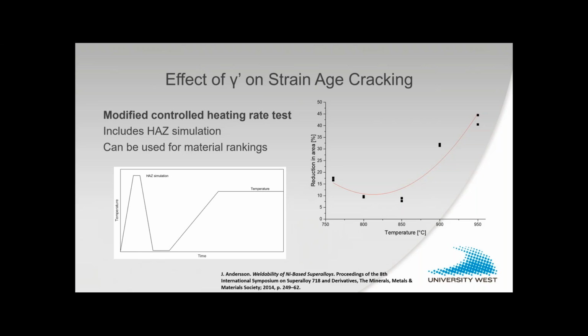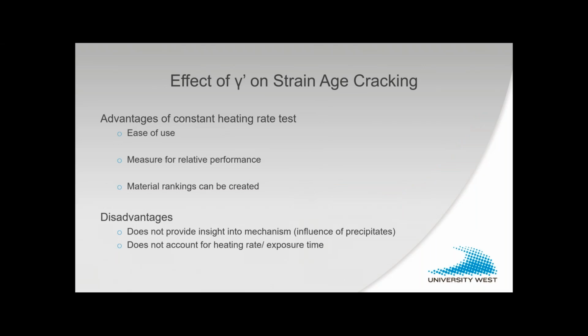So benefits were, for instance, it was very easy to use this type of test, and the relative performance in between the different materials and rankings were good. But as I said, no insight to the actual mechanism, like the influence of precipitates, and accounting for heating rates and exposure times becomes a bit tricky.